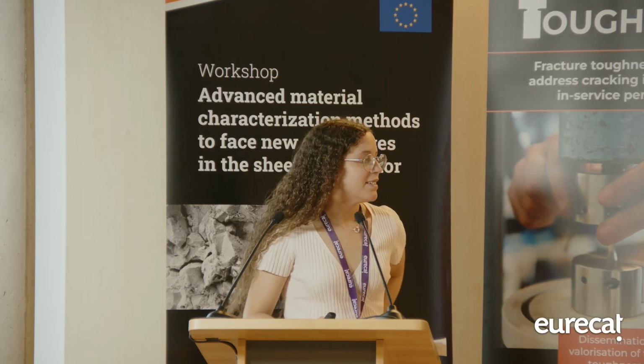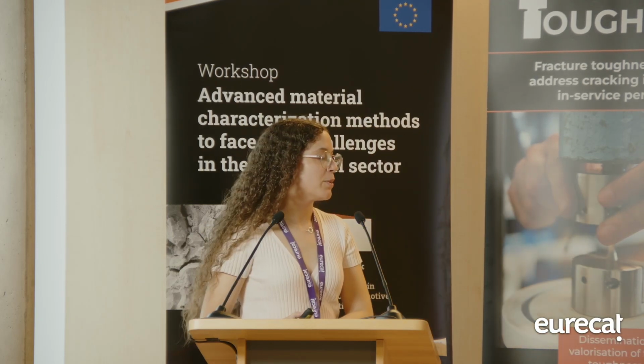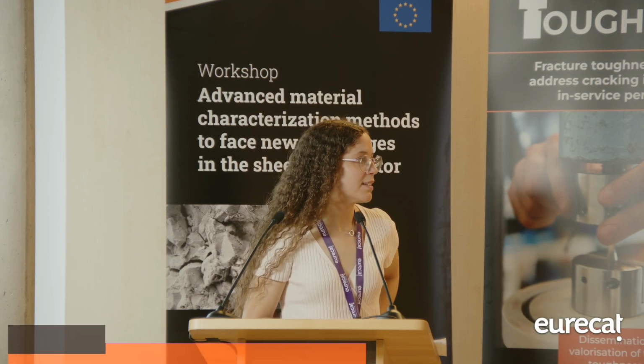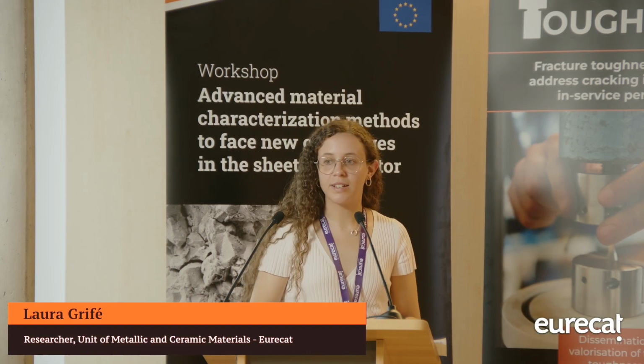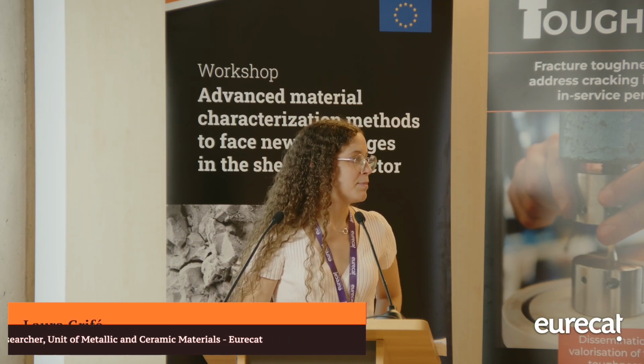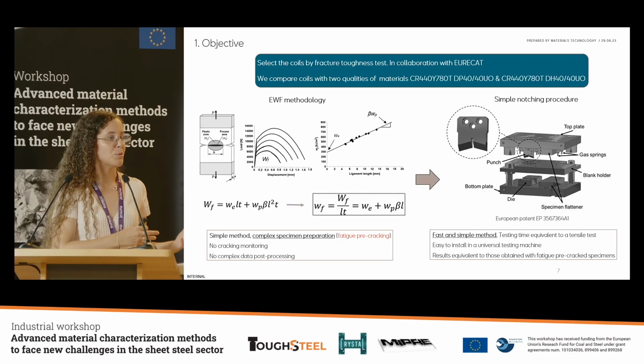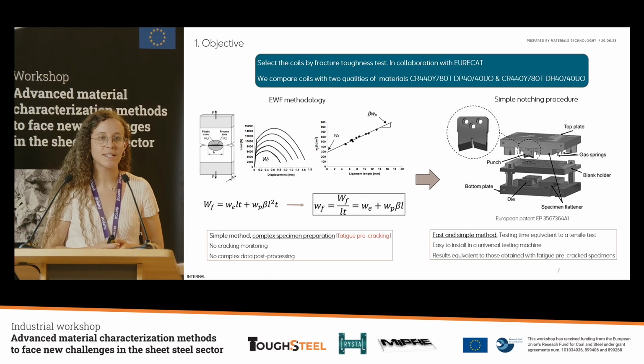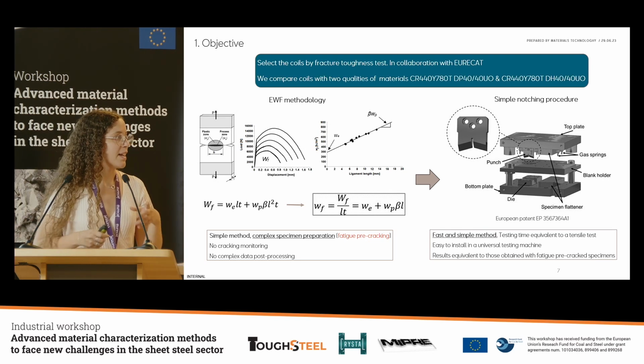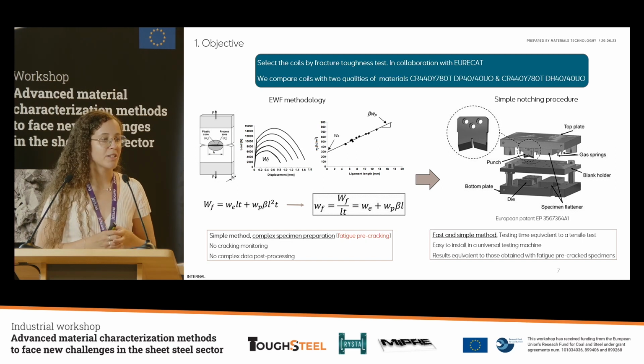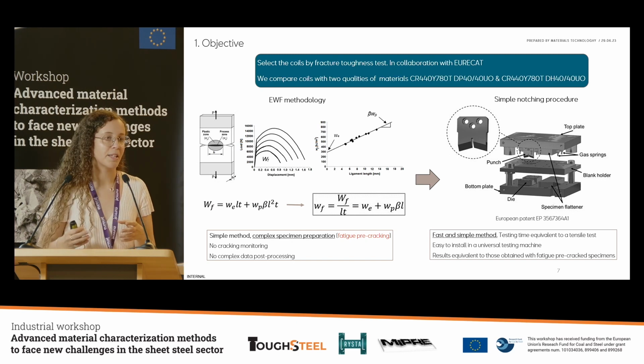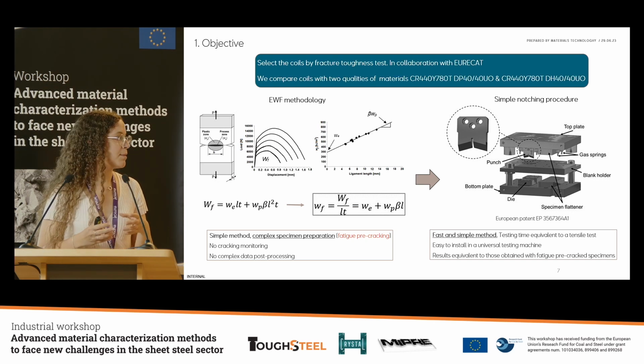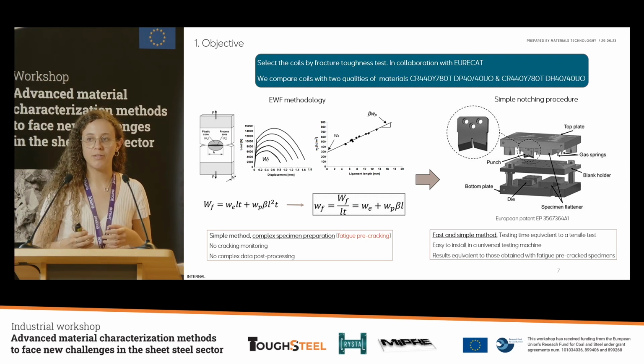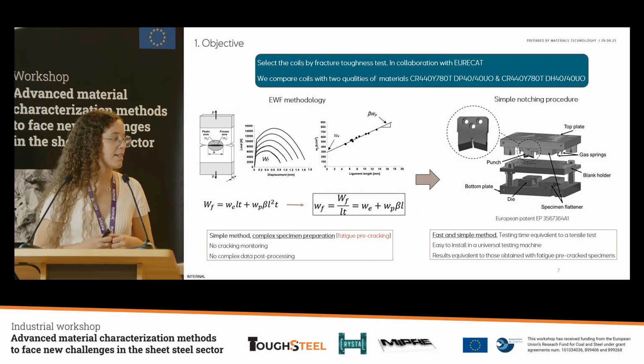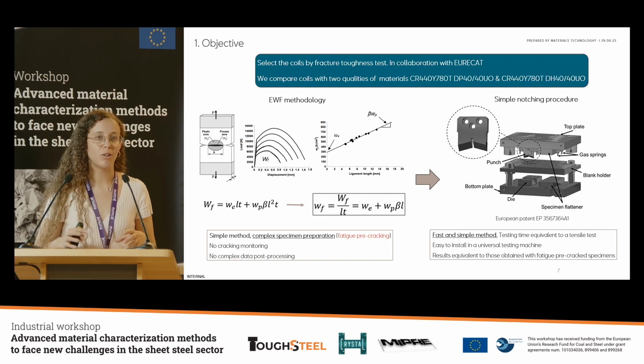Thank you, Noemi. So yes, with this problem that they presented, we wanted to try the essential work of fracture method, but we wanted also to give them the opportunity to do the tests. We decided to do the essential work of fracture method, which is a simple mathematical method. However, the specimen preparation is quite difficult because we need to propagate cracks, and this takes time, and it's complicated to control all these parameters.